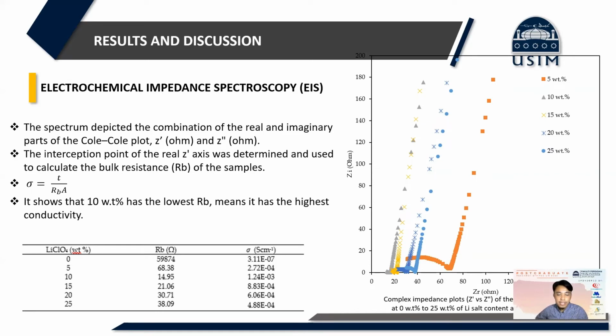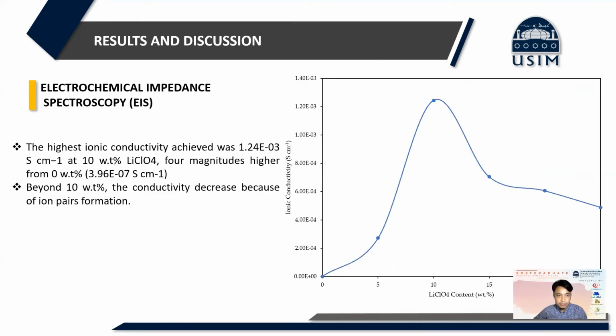The conductivity is calculated by this formula. Conductivity equals the thickness of the sample over bulk resistance times area of the sample. The highest conductivity achieved was 1.24 × 10^-3 Siemens per cm at 10% lithium perchlorate, which is 4 magnitudes higher than 0%, which is 3.96 × 10^-7 Siemens per cm. Beyond 10%, the conductivity decreased because of the ion pair formation. The ion pair formation will be discussed more in the FTIR part.